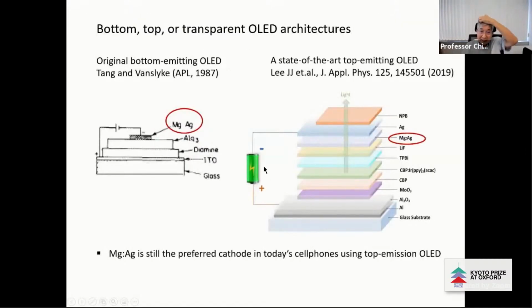So I just want to point out that some of the work that we did in '87 is still being used today. So the 2-layer structure expanded into the 7-layer structure, but some of the electrodes remain somewhat unchanged. So for instance, this magnesium silver that we discovered, or we developed in Kodak, was still being used for the top emission OLED, even in today's cell phone structures, because these turn out to be one of the best semi-transparent electrodes so far.